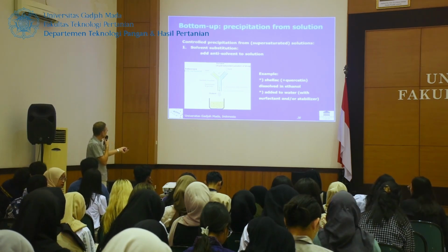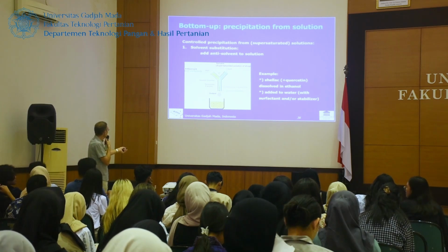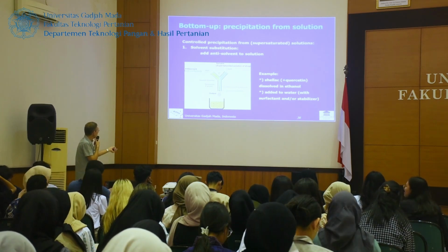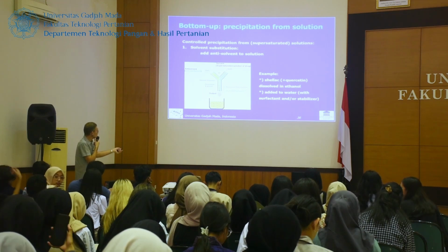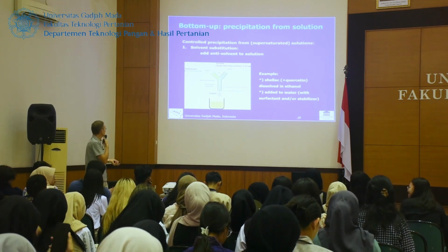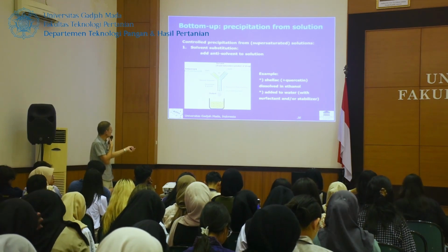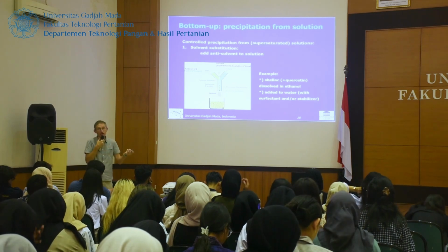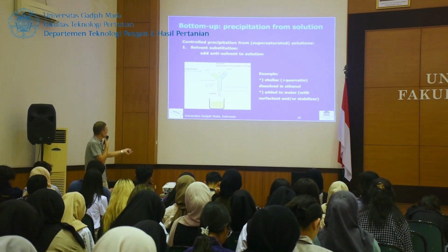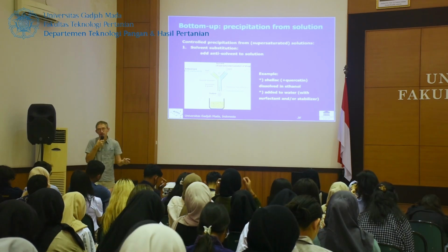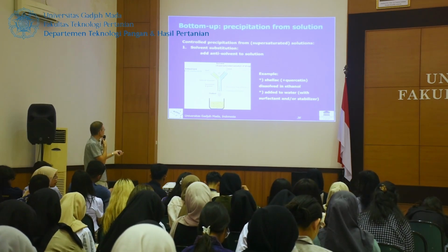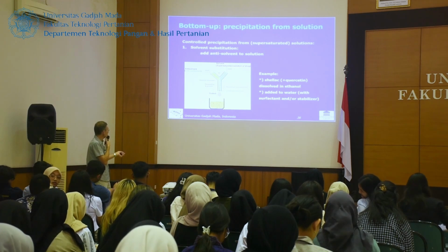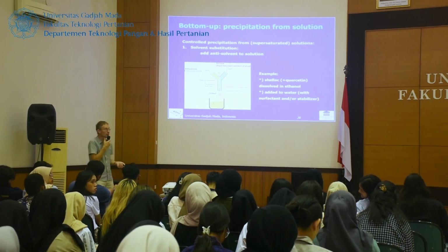So if you start from a solution of your polymer in ethanol, and then gradually mix that ethanol solution with water, as your shellac experiences a higher and higher water content, it will start to precipitate, and as such you can form shellac particles in water. So that's a way to make nanoparticles.